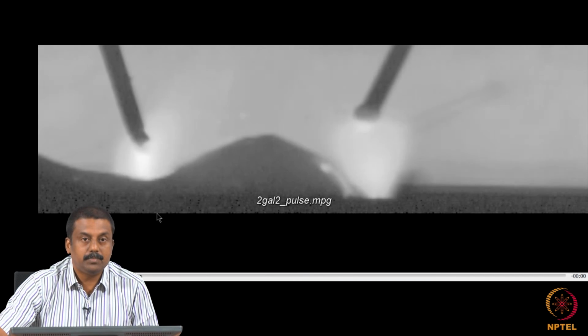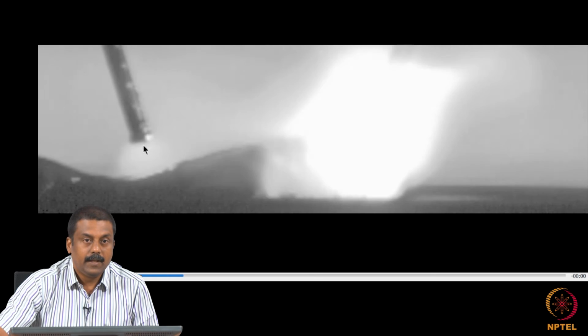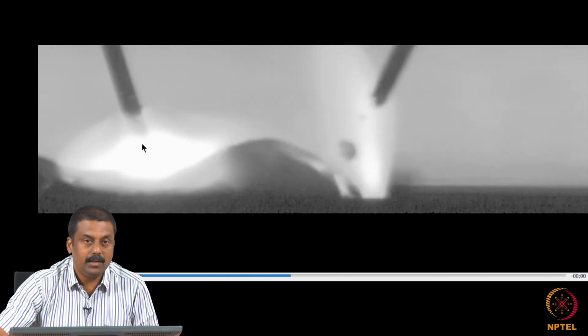So the main advantage of this process, pulse GMAW, is that we achieve spray transfer at a much lower mean current than a conventional GMAW, and because of that we reduce the heat input significantly.